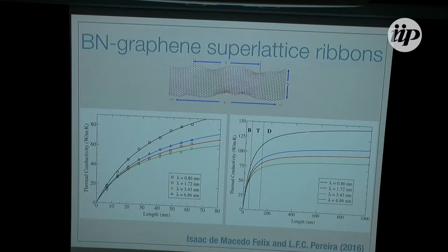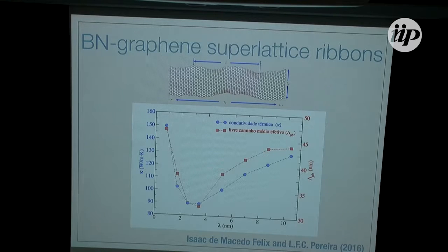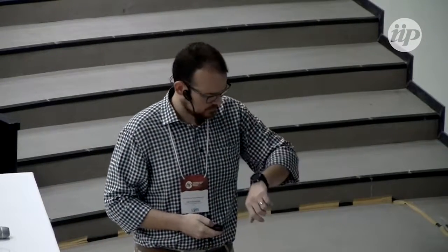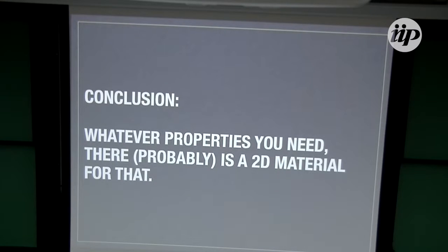So we begin with a high value for a small period, and then we increase the period and the thermal conductivity decreases. We increase the period a bit again, it decreases again, but then when we increase the period again, the thermal conductivity goes back. So it's a non-monotonic dependence. The thermal conductivity has a minimum at a certain period length. We are working on explaining this behavior in terms of coherent and non-coherent phonon transport across these interfaces. Now, to conclude, I'm still on time. Whatever properties you want to find in a material, there's probably a 2D material that has that for you.